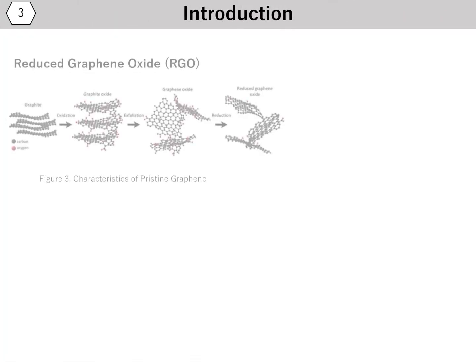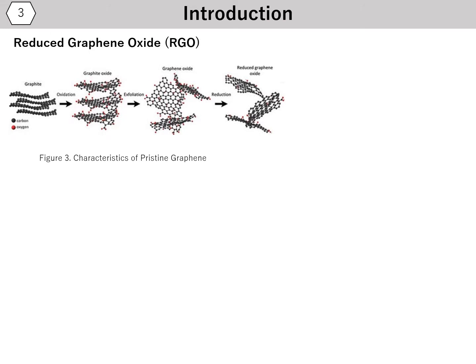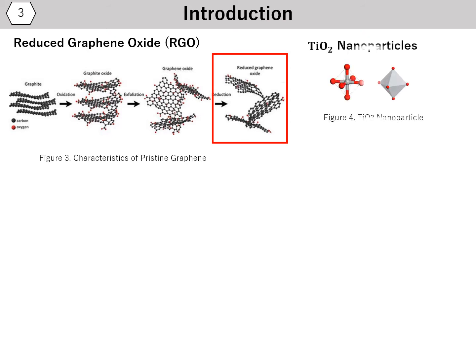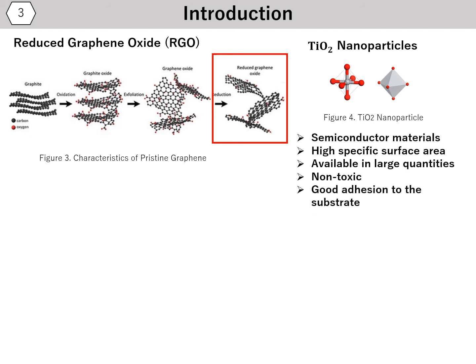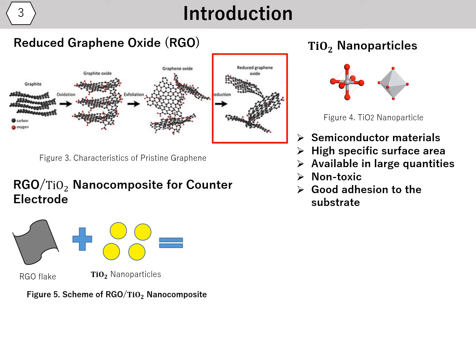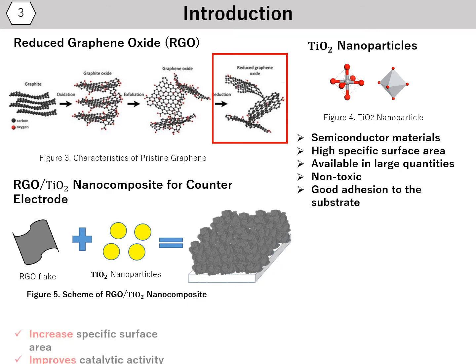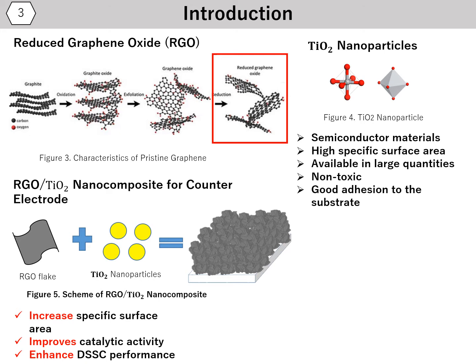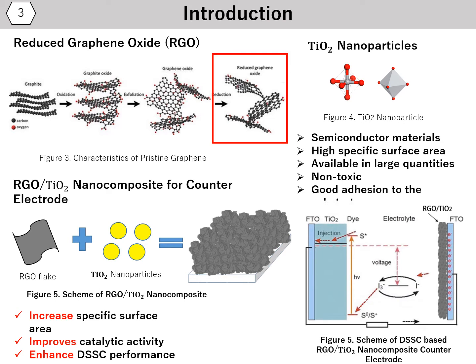For large application, we can use graphene-like material, which is reduced graphene oxide, or RGO. Another nanomaterial is titanium dioxide nanoparticle. Titanium dioxide is a semiconductor material that has high specific surface area, available in large quantity, non-toxic, and good adhesion to the substrate. With those advantages of RGO and titanium dioxide, we can combine this material to be RGO titanium dioxide nanocomposite for counter electrode in dye-sensitized solar cell. It can increase specific surface area, improve catalytic activity, and then enhance dye-sensitized solar cell performance.